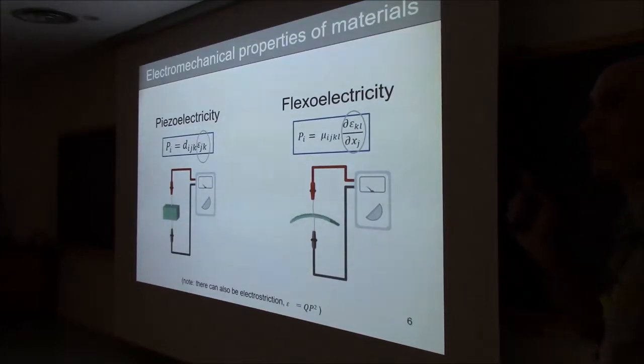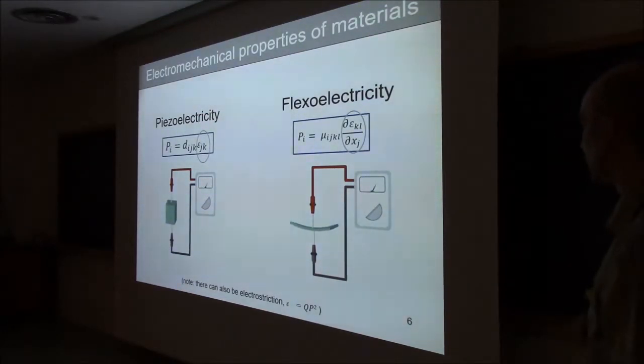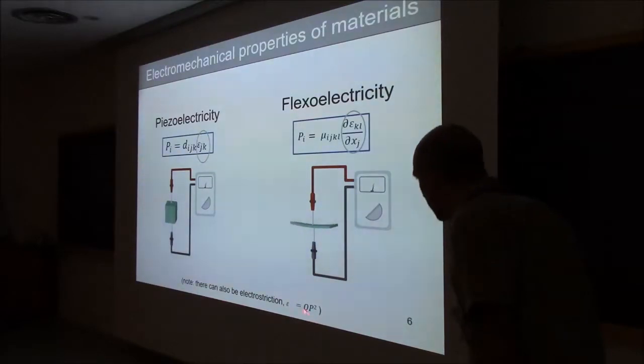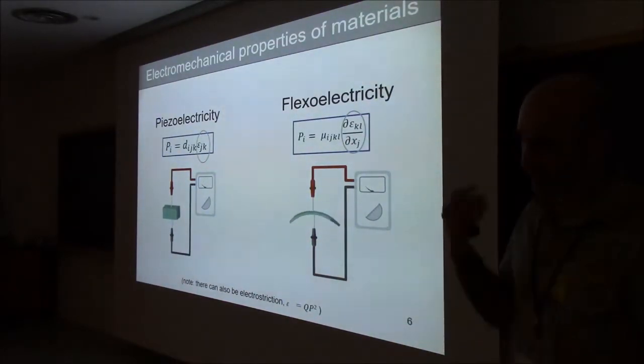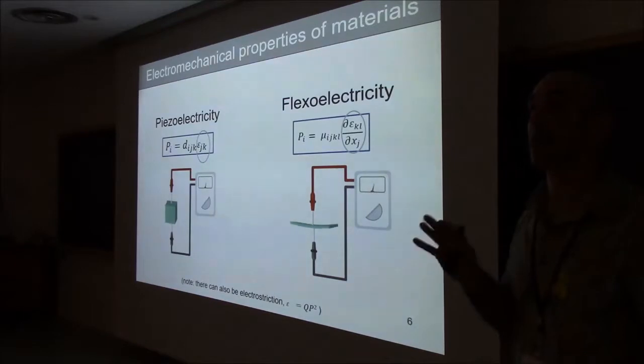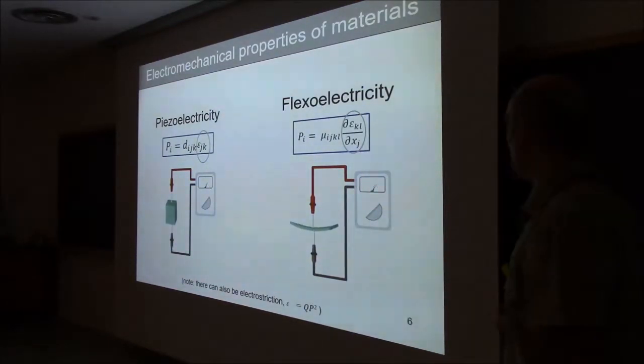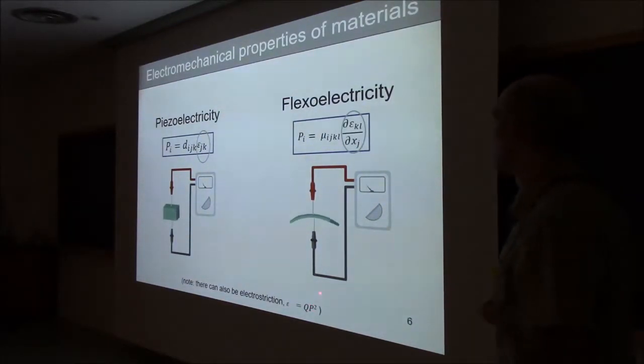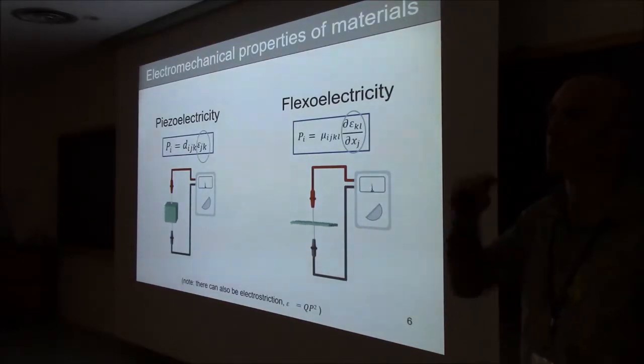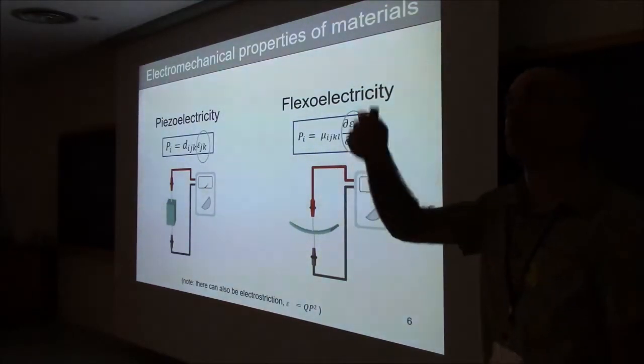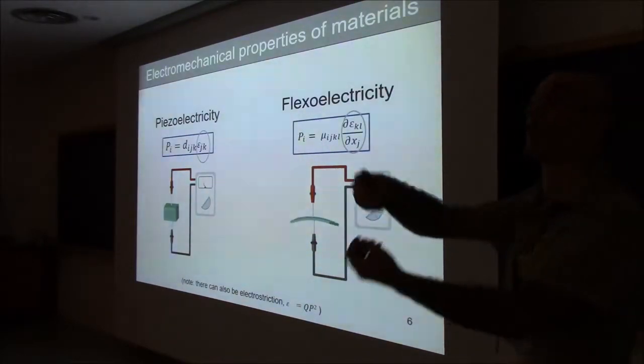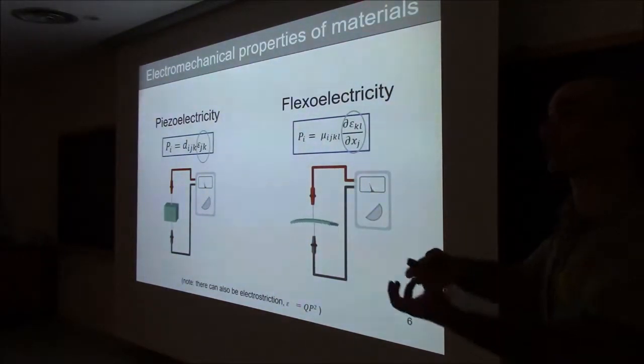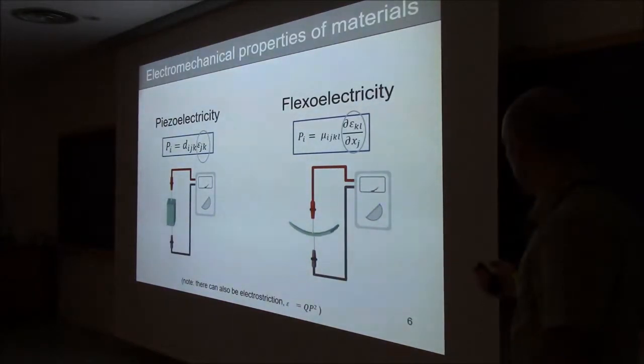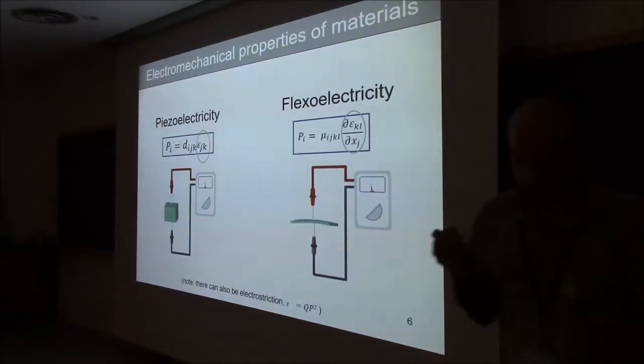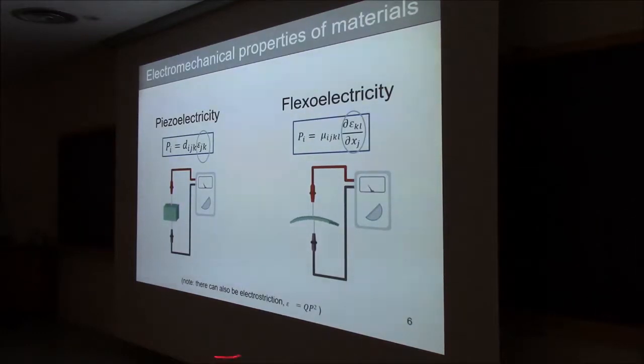Someone this morning asked me about electrostriction. I'm not going to discuss electrostriction, but I should mention it. So another electromechanical property that is allowed by symmetry in all materials is electrostriction, which is a strain proportional to the square of the polarization. And again, you can start with something that is centrosymmetric, you apply an electric field, the electric field breaks the symmetry and gives you a polarization, and then you get a strain that is proportional to the square of this polarization.